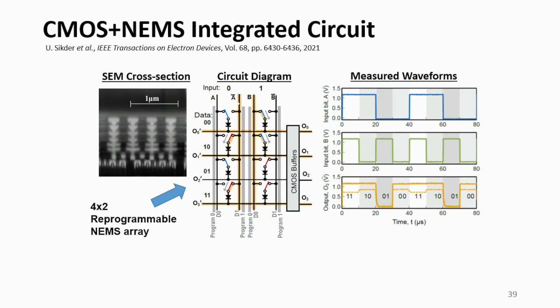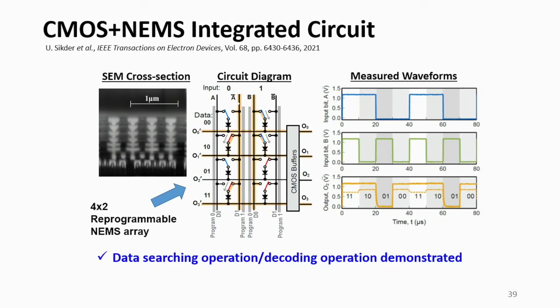Okay, so in this particular example here, the switches in the first row, which corresponds to a data input string of 0, 0, are each programmed to touch the data 0 line. And if you look closely, the second row corresponds to an input string of 1, 0. So the switches are set to store 1, 0. So it just turns out when you apply the voltages to the input lines, only one of those horizontal bit lines is actually pulled low. So you can think of this as a decoder circuit. And the measured waveforms on the right show that this works properly. And you can reprogram the switches, so you can actually update the functionality of this circuit over time.